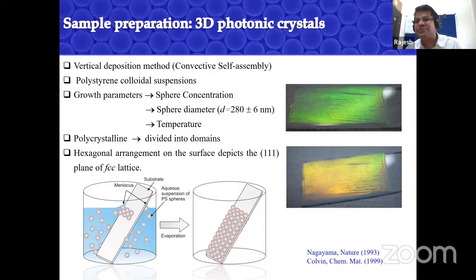And this is exactly what you see in the peacock feather, which I showed in my first slide. So imagine different kinds of photonic crystals stacked together, you will have a very beautiful coloration. And this color, as I said, depends on the diameter of the spheres or the refractive index of the material. And if you slightly tilt the sample, you see a bit of orange or yellowish colorations. So you have different colors, because it's angle dependent.